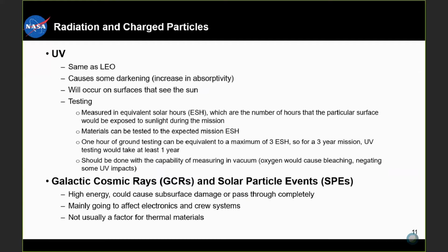Unfortunately, that would take forever if we had to do it in real time, but 1 hour of ground testing can be equivalent to a maximum of 3 ESH. So for a 3-year mission, UV testing would take at least 1 year if you wanted to do the entire 3 years. The good thing about this is that UV damage usually follows a curve, so it sort of flattens out the further down you go. So the longer you're up there, you get a little bit less damage. So most damage takes place earlier.